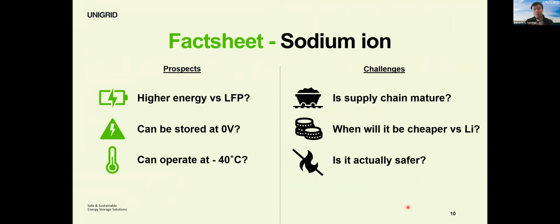Before I end, I just want to discuss some prospects and challenges of sodium ion, often talked about, but maybe not addressed often enough. Some of the prospects include, firstly, does sodium ion have a higher energy density than LFP? Yes, this has been proven not just by us, but many other teams out there as well. Secondly, can sodium ion really be stored at 0 volts? As Ruth showed, the data for sodium ion is tolerant to over-discharge, so you can store it at 0 volts for long term, transport it, and reduce a lot of your hazard risks. Third, can sodium ion really operate well at sub-zero temperatures? And this is a big yes. Below 0, you can still get more than 90% of a sodium-ion cell's energy density capacity, compared to maybe only a fraction in LFP.